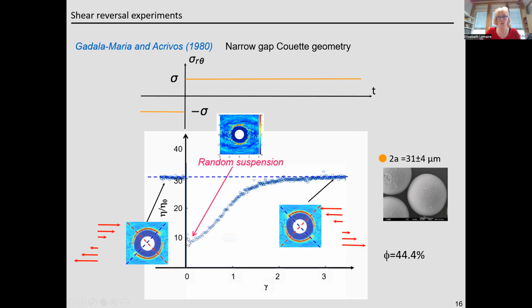And just after the shear reversal, to pass from this microstructure to this one, we have to break this microstructure. And when the microstructure is broken, then we have an almost isotropic microstructure with a few contacts between particles. Okay, so that means that the difference between the steady viscosity, where we have contacting pairs of particles, and